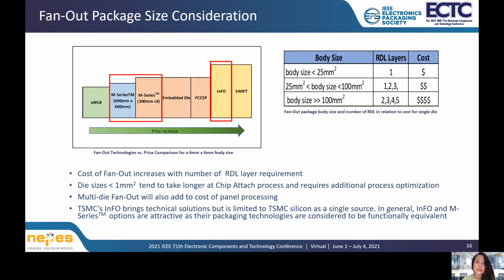For example, a die size of less than 1 mm squared may take upwards of 8 hours to complete the chip attach process on a 600 mm panel, as opposed to die sizes larger than 25 mm squared at less than 1.5 hours. Assuming all gantries are simultaneously picking and placing the die at chip attach process. The material, time, and cost consideration for smaller die sizes must be taken into account and may skew baseline pricing